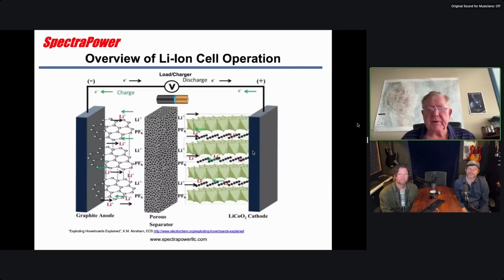So you build the cell with the lithium and the cobalt and a little bit of lithium in the electrolyte. The electrolyte is typically a carbonate, a carbon-based electrolyte: diethyl carbonate, dimethyl carbonate, things like that. They're usually mixed combinations, and it's most often in a liquid form. And then over here on the left is the anode, and that's graphitic, a graphitic carbon.